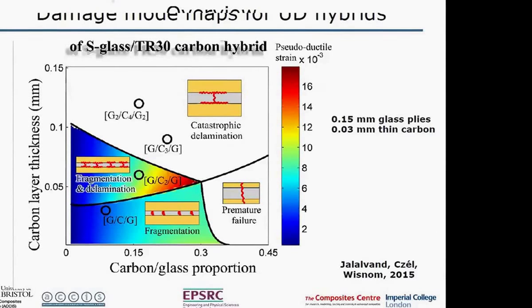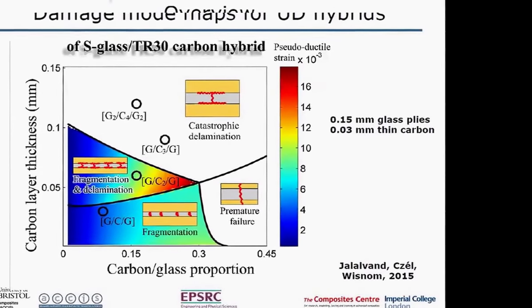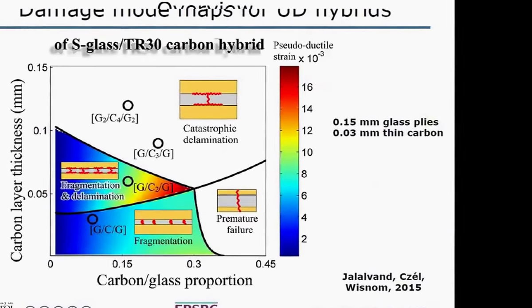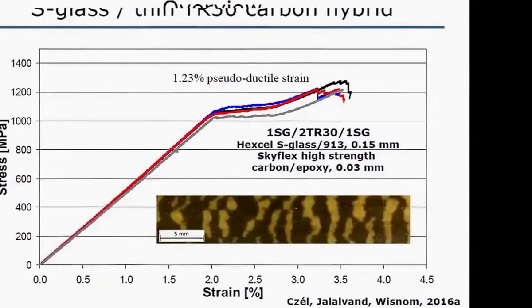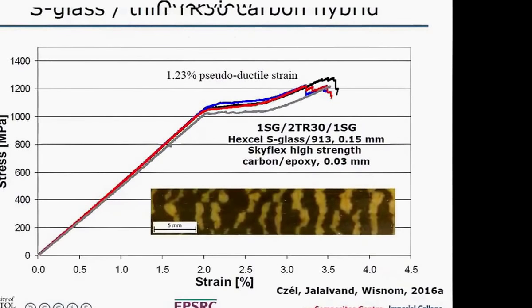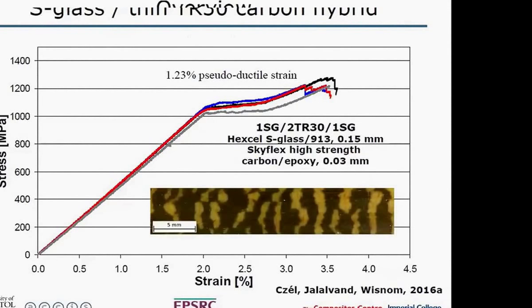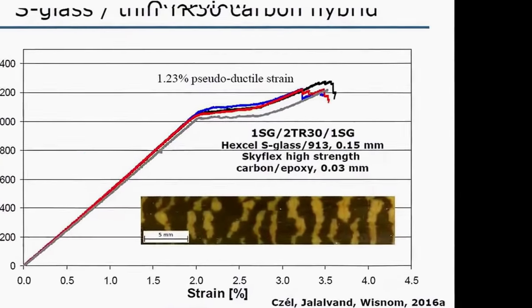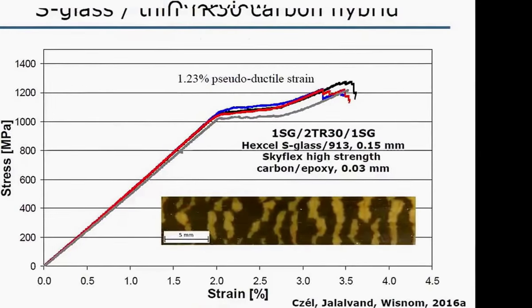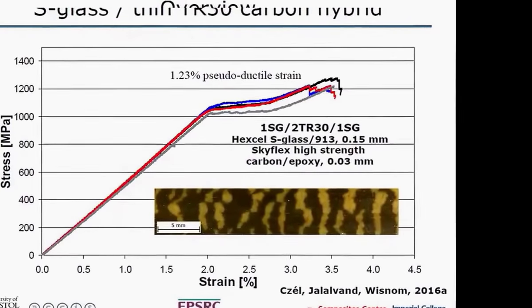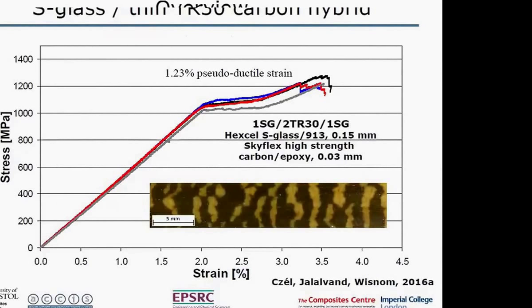So a lot of modelling work has been done by Wisnom on this to be able to predict the behaviour for different combinations of materials. So this shows one example here, where this is the same material, which is S-glass, standard thickness with these thin TR30 high-strength carbon fibre plies. And you see we get this plateau here on the stress-strain response, with in this case 1.23% pseudo-ductile strain. We're defining the pseudo-ductile strain as the extra strain we get over and above what you would have by an elastic response at that same stiffness. So the distance on this plateau is what we're referring to as the pseudo-ductile strain.